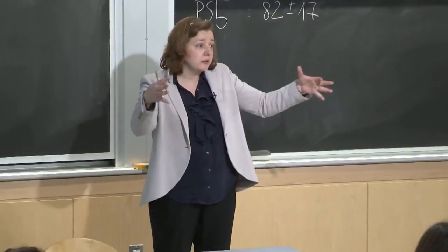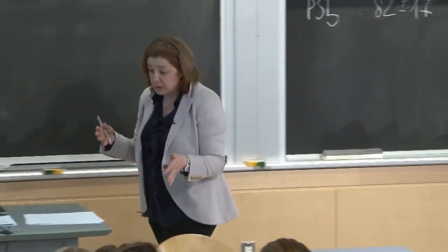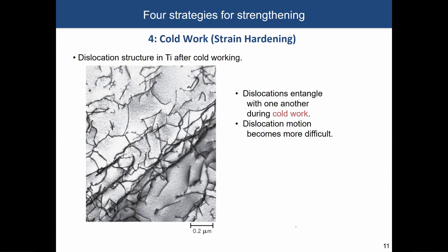You start with a relatively modest density of the dislocations. You increase this by orders of magnitude. And just a typical image of a hard work material is given here. So again, these would be dislocations. So dark lines here indicate dislocations. So this is an electron microscopy micrograph showing dislocations in a case of titanium after cold work.